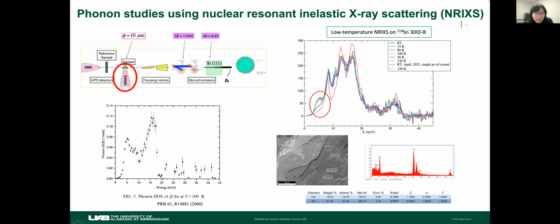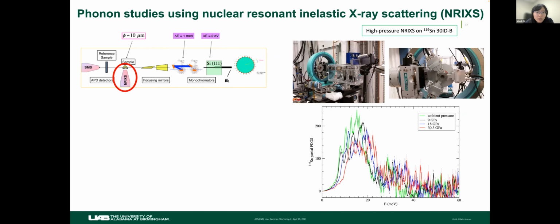So later on, every time we load a sample to study phonon magnetism, we try to screen the single crystal ahead of time to make sure of the purity. And this is one of the runs. We loaded a purer crystal in a diamond cell and did tin NRIXS experiments under high pressure up to 30 GPa. And again, we consistently see this shift of the phonon modes; they harden.